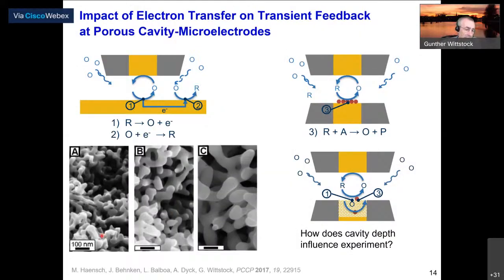Okay, now this is the nanostructure of that nanoporous gold. We can tune the size of these ligaments and the pores by different processes, and now we would like to investigate the surface chemistry of that. But there is, of course, an issue in that, because we need to worry about the situation that the parts which are close to the outer surface of that cavity electrode are more easily accessible to the mediator than parts in the inner filling of that cavity microelectrode. And that is a completely different situation to what I showed you at the beginning, where all the adsorbates or surface oxides are at the outer surface of such an electrode. So we need to answer the question whether this is good or not.